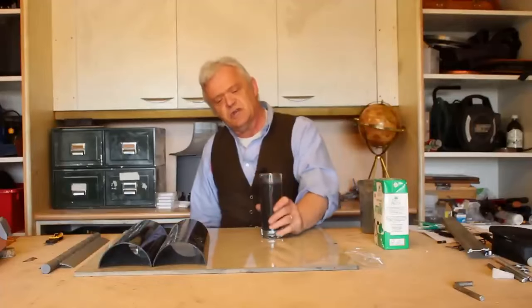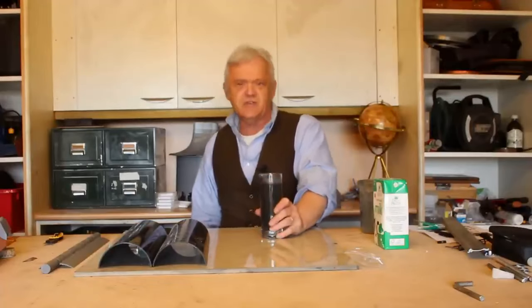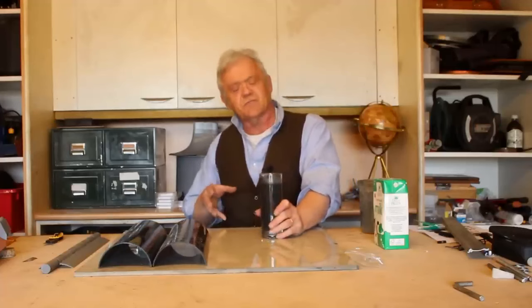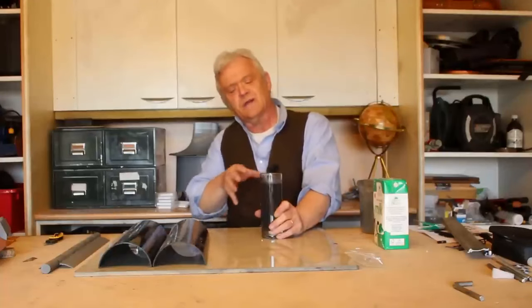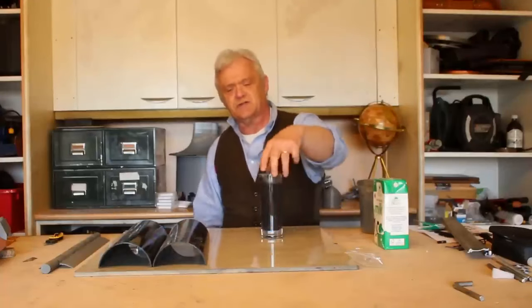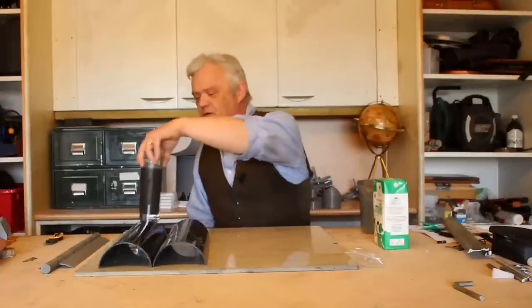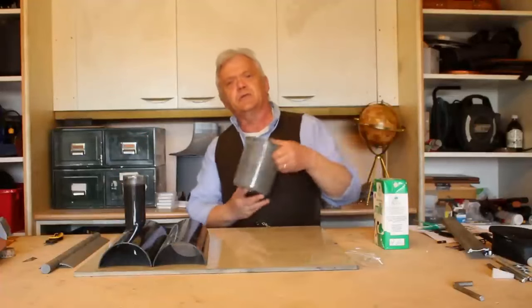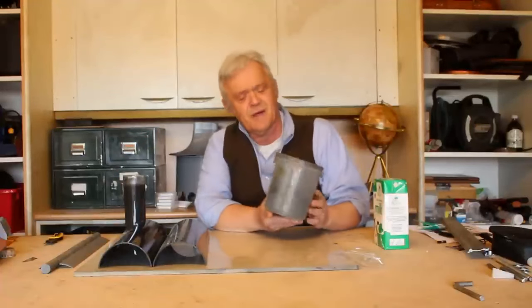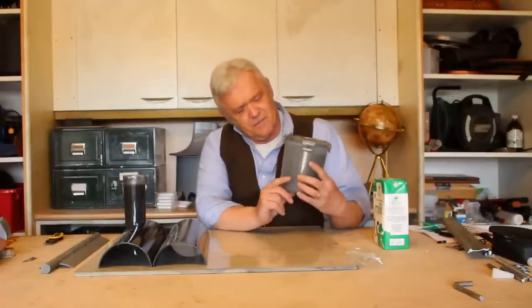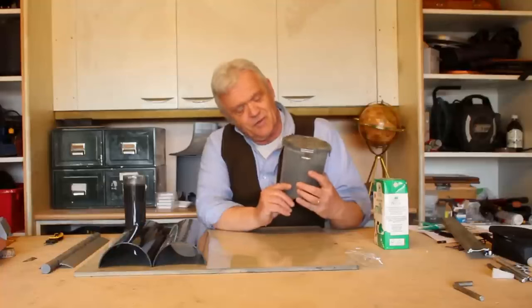Now we've got two choices here. We can either leave this as is and put it into something, or we can dry it. Now drying it's really easy. You just spin it up in a centrifuge at 1500 RPM for 45 minutes, set it out to dry, and what you'll get is a whole bunch of this stuff, which is graphene powder. Because it's graphene powder, we then want to do something with it.